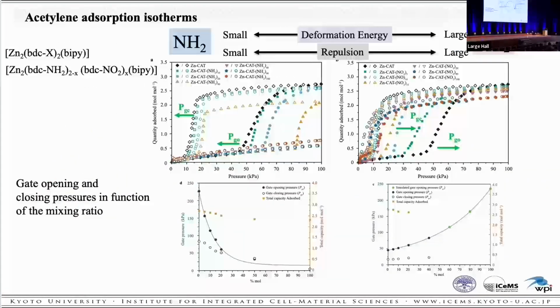The deformation energy is large for benzene dicarboxylate with nitro substituents, while that for BDC with amino group substituents is small. Therefore, the gate opens in the high pressure region for the MOF with more nitro content. It is clearly observed that the gate open and close pressure of the adsorption isotherms depend on the amount of the substituent.